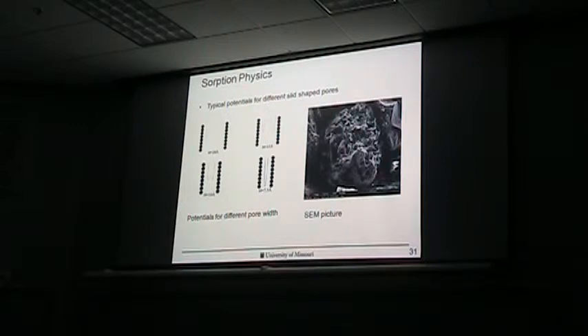This is also another SEM picture where you can see these holes we have, the pores. And you see these are potentials for different pore sizes. You can see if the pore gets smaller, you get a deeper potential, which means you can absorb more gas. But the problem with these deep potentials is that you can't remove the gas so easily anymore. So you have to balance how strongly you want to basically bond them or not.